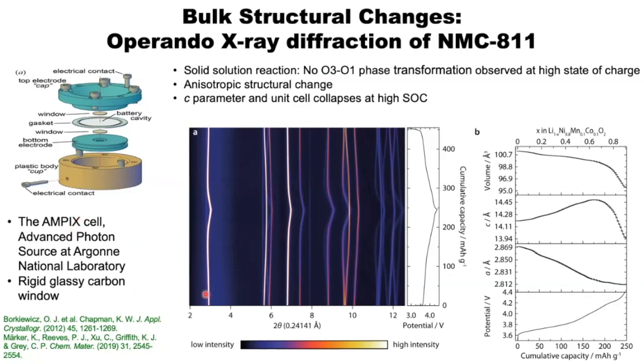And so this is a classical in situ NMR, in situ diffraction study of NMC 811, showing the classic changes. This is the 003 peak. You see it shifting, first of all, to lower 2 theta, and then up to higher 2 theta, which you can then, from a refinement, see the classic pattern of a layered structure where the layers expand, and then they compress above about 0.7. X is 0.7 removal from the material, or about 200 milliamp hours per gram.